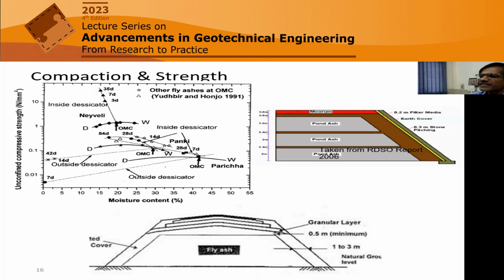Or in fact, in another fly ash which had approximate strength at OMC of 0.04, it has reduced to 0.003. So a 10 times reduction in the strength as the moisture dries out. So this moisture content must become 0. So this finding, what's the implication? So this is the